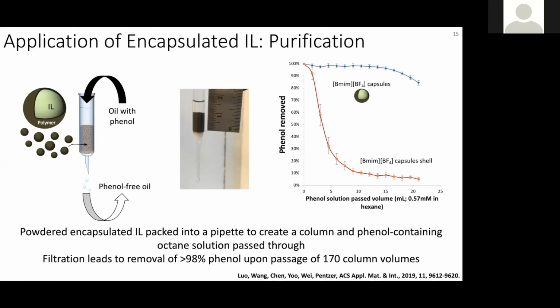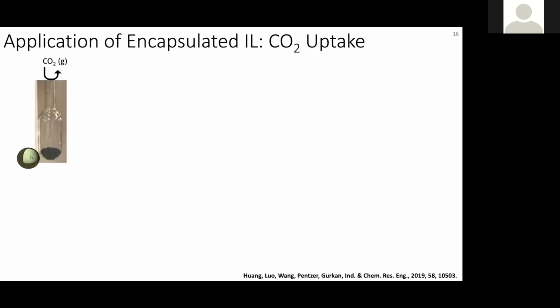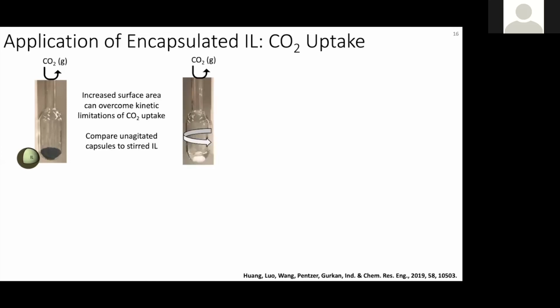In a collaboration with Professor Burcu Gurkan at Case Western Reserve University, we looked at the CO2 uptake of the ionic liquid when encapsulated versus the ionic liquid when it's neat. And so ionic liquids have a high solubility of carbon dioxide, but an issue is that in order to make use of that high solubility, you have to have a high enough surface area. So you typically have to mechanically agitate the ionic liquid in order to reach equilibrium of the system.